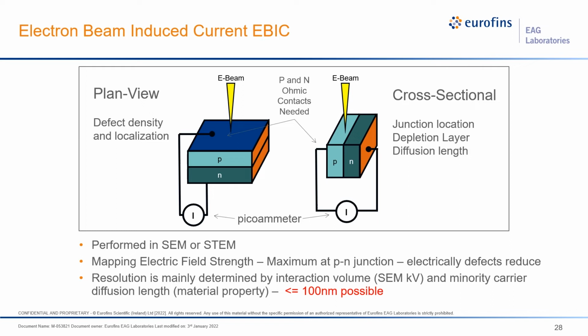Ultimately, for cross-sectional EBIC, you're going to want samples that are typically cleaved, but we can also do focused ion beam cross-sectioning as well, and have good experience creating low damage, low implanted cross-sections to still be able to do EBIC.